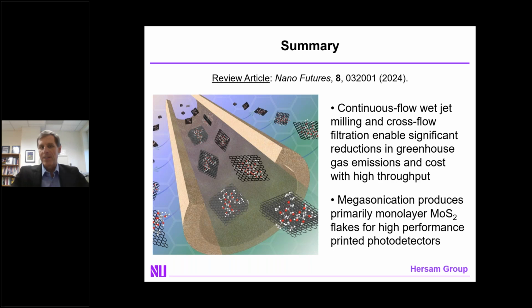So with that, I think I'm out of time. I'll quickly summarize. The first point I tried to make today is that continuous flow wet jet milling combined with continuous flow cross-flow filtration allows you to sustainably produce large quantities of 2D nanoelectronic inks. And then the more recent innovation of megasonication allows us to now exfoliate down to the truly monolayer limit, getting direct bandgap character, which is suitable for high performance printed photodetectors.